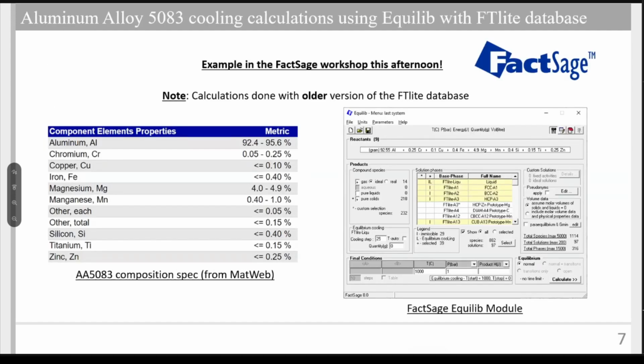At the beginning of my project, I wanted to look at real alloys and to see which phases are formed. So using FactSage, and once again, this is another example we'll see this afternoon, the use of FactSage for cooling calculations. Also make a note that the calculations I've done here are using an older version of the FT-Lite database, so results may vary. I started with the 5083 alloy. You can see the composition limits in the table on the left that I pulled from MatWeb. Using the FactSage equilibrium module and selecting the appropriate phases, and I'll cover this in the afternoon, on how to select the right phases to ensure that the simulation does not last too long.